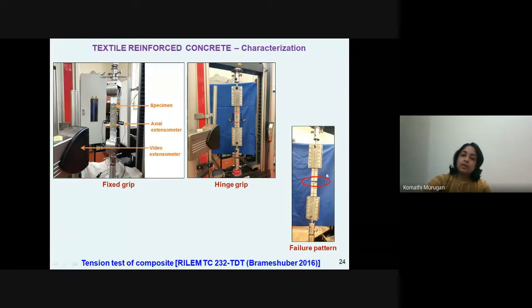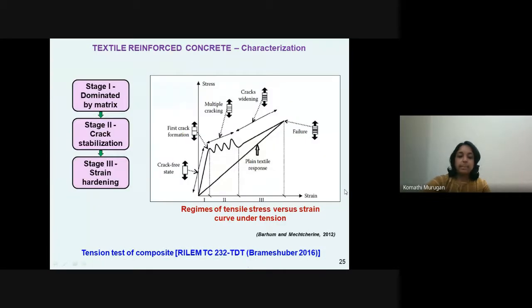Typically, what happens is the concrete starts cracking, and ultimately at peak the textile ruptures, and beyond peak there is also a certain ductility, after which we stop the test. This picture shows the regimes of the tensile stress versus strain curve for such a composite panel tested under tension. This can be very much compared with the RC behavior, or the behavior of the system with steel reinforced concrete.